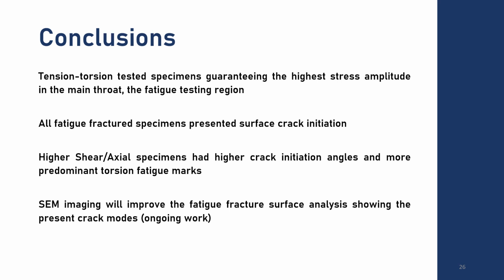Regarding tension-torsion method conclusions. All tested specimens guaranteed the highest stress amplitude in one single fatigue testing region, the intended and denoted main throat. All fatigue fracture specimens presented surface crack initiation, which was predictable. Now, looking at the shear axial ratio, as the shear and axial ratio gets higher, higher crack initiation angles are obtained and more predominant torsion fatigue marks are obtained, associated with higher shear damage.